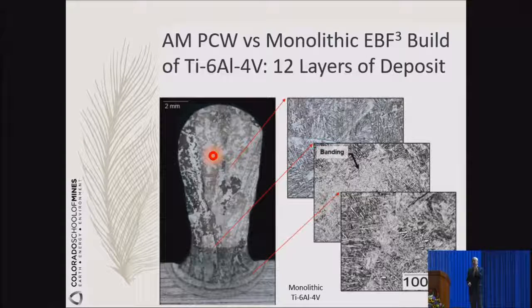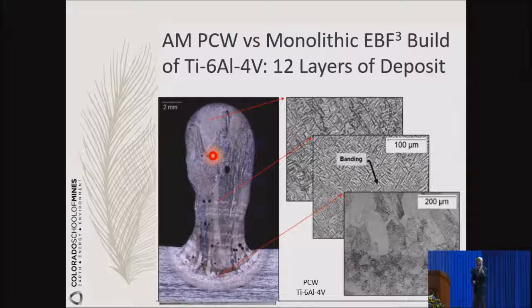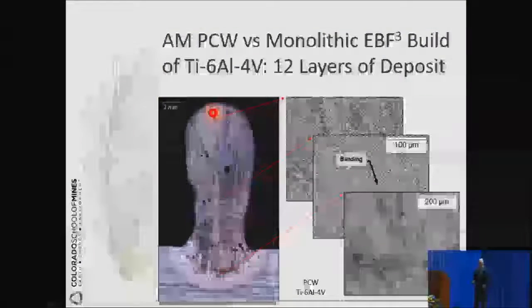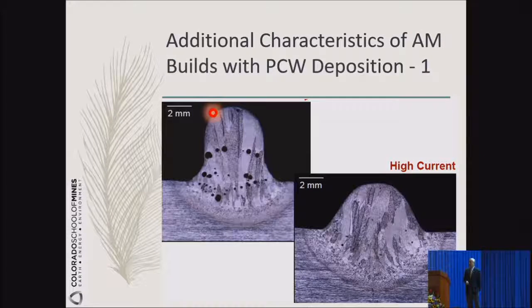If we switch that to the powder core to compensate for the composition loss, what do you see here? You see the presence of pores. Because of the inherent properties of the powder that you use, when you deposit, now you generate this porosity. Now, what are these characteristics? Maybe oxygen, maybe nitrogen. Some of these oxidation products decompose and then release it. So now you have all these pores. But the characteristic of epitaxial growth continues, okay? All right. It can be removed, okay?